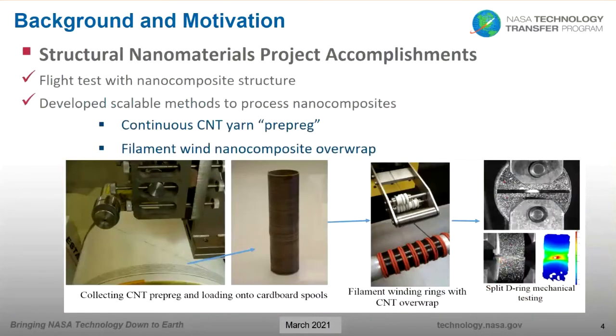We believe that we had many accomplishments working on this project, the most obvious being involved in the process to do a flight test demonstration with the nanocomposite structure, but there were also materials development successes as well. Through this project, we developed a controlled and continuous process to infiltrate resin into the carbon nanotube yarns, making our own prepreg material. And we did this using lab equipment that was used for making prepreg from other fibers.